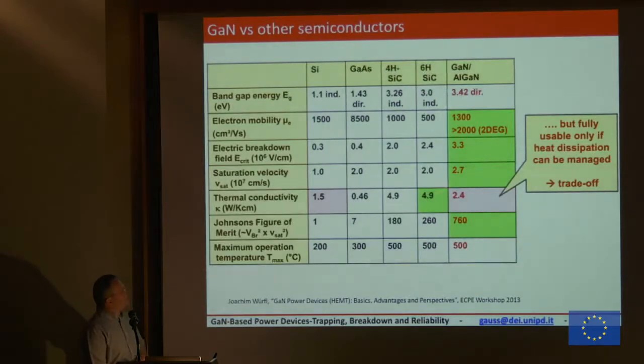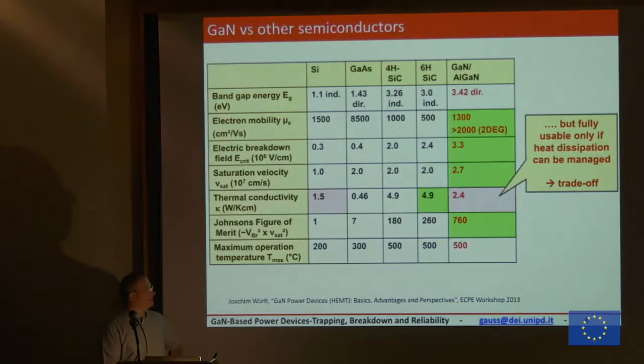Of course, this is the table that we have seen. One little drawback that we may see in gallium nitride: you see a lot of very good green area here, so very good mobility, high electric field, and very high saturation velocity. A little weak point of gallium nitride compared to silicon carbide is the thermal conductivity. So we really need to cool down the device in the self-heating case. It's not about being able to operate at a higher temperature, but the necessity to cool down the device, because at the end, any reliability issues, as we will show you later, are temperature related. So the cooler the device, the better it is for reliability, even if we can push higher than the silicon.